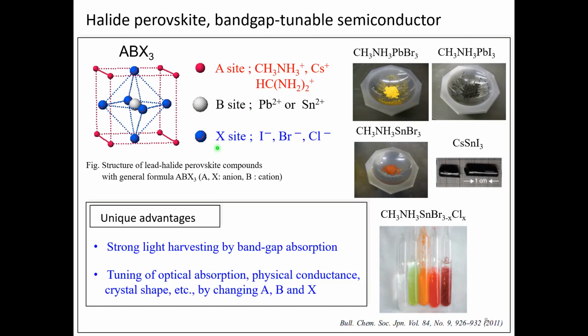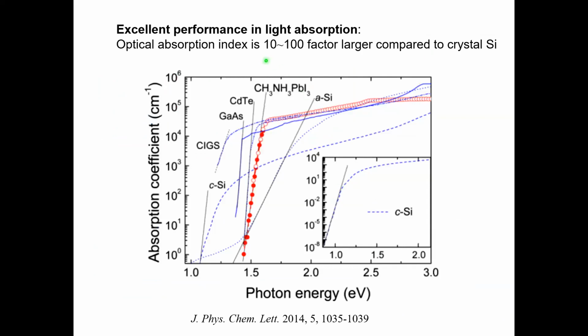So we can dissolve the materials and coat on a substrate, and just by drying the layer, we can deposit crystalline perovskite. Here you can see black perovskite and a yellow one. This is made by just changing the halide element from iodide to bromide. So we can easily change the color and band gap of the semiconductor. One excellent performance is light absorption power. This power is 10 to 100 times larger than crystalline silicon.